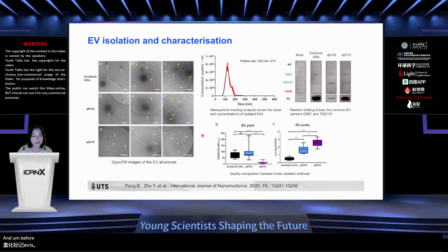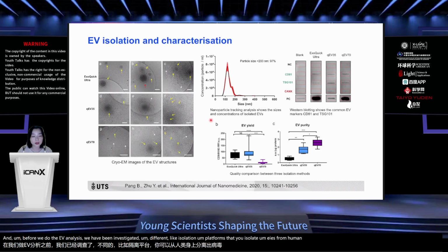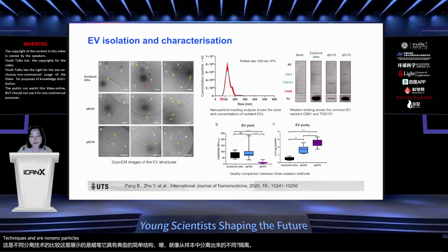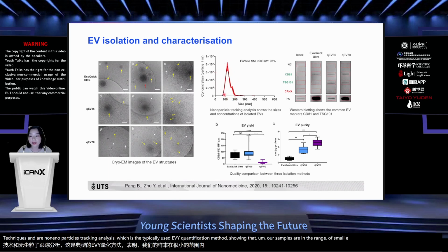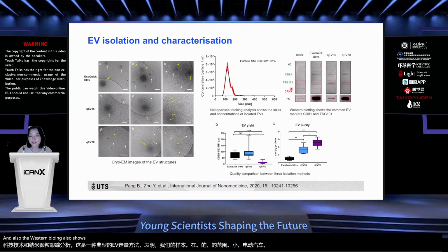And before we do the EV analysis, we investigated different isolation platforms to isolate EVs from human plasma samples. Here is the comparison of different isolation technologies. Here we show the cryo-EM, with the typical EV structures from the samples isolated by different techniques, and nanoparticle tracking analysis, the typically used EV quantification method, showing that our samples are in the range of small EVs. The Western blotting also shows our samples contain commonly used EV markers such as CD81